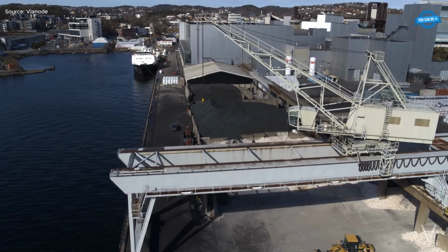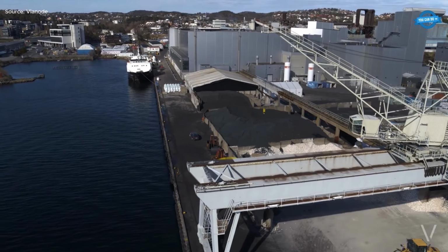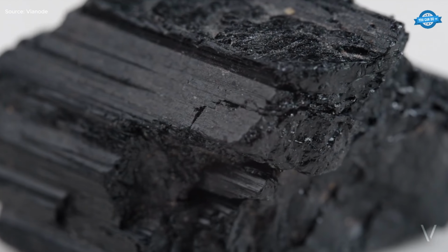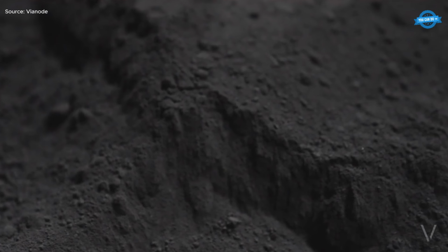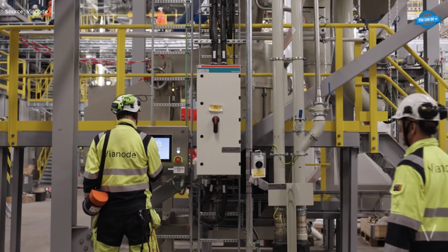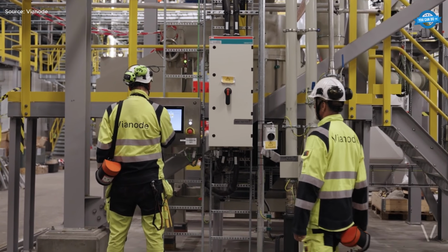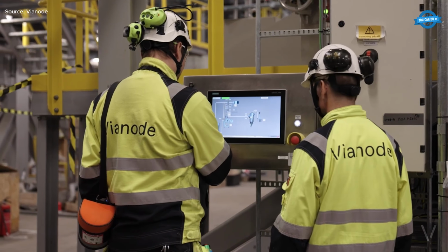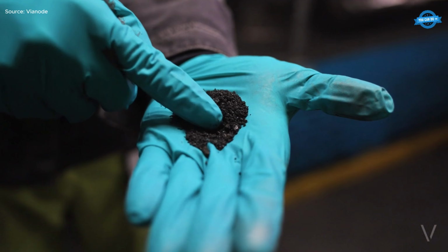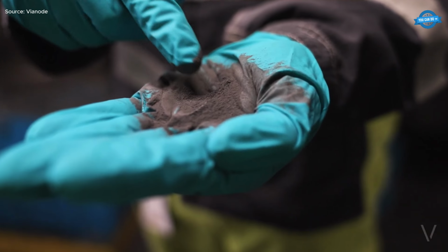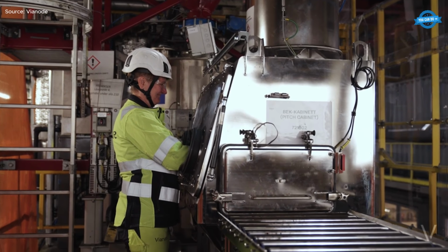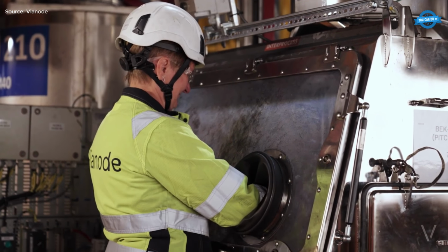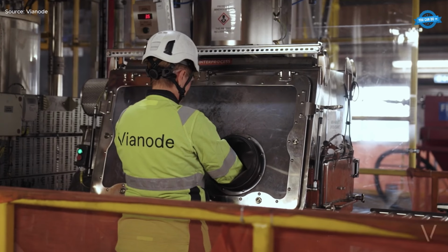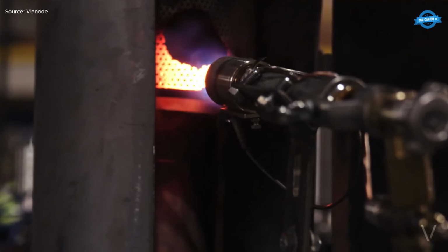Synthetic anode graphite at Vianode is produced through a tightly controlled sequence engineered for battery-grade purity. Petroleum coke is first crushed, dried, and demagnetized before precision milling generates the target particle size and morphology. Impact milling further increases surface area for lithium-ion intercalation. Subsequent shaping rounds particle edges to improve packing density.